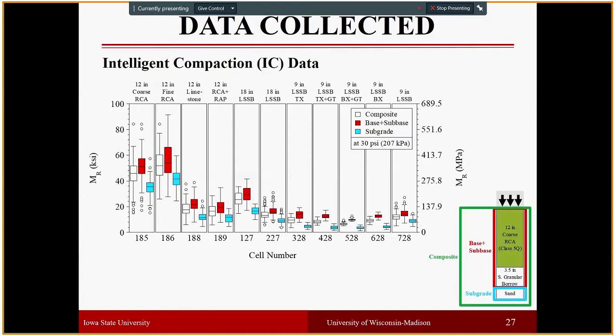And one thing that we wanted to point out, if this is consistent with all LWD, FWD, and intelligent compaction data, to see the benefit of geosynthetics, really you need the FWD or these residual modulus, the APLT and LWD test, the load that we apply is not adequate to really see the contribution of the geosynthetics. So we don't want to get any conclusions that geosynthetics didn't really contribute. In fact, it really contributed during the construction stage because subgrade was too loose and geosynthetics really hold the large stone subbase layers pretty well intact. But to see the real contribution of these geosynthetics, we really need to apply much higher loads than what FWD or automatic plate load test or LWD tests can apply.